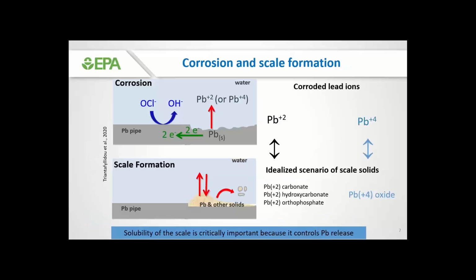So if we look at the schematic here on the top, this is a cross-section of a lead pipe. You can see the lead pipe wall represented by gray at the bottom of the schematic, and then you can see the water with light blue on top. And you can see that corrosion process and the reactions that I showed you earlier depicted on the pipe wall, and the leaching of lead +2 or lead +4 corroded lead ions into the water. This is the first part to metal release, but not the most important one.